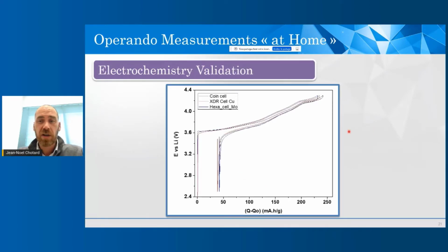So we have to check also the electrochemistry of our cell, and I'm comparing here the galvanostatic curve of NMC material, so lithium, nickel, manganese, cobalt oxide. Maybe it's not that visible, but you have a black, a red, and a blue curve right here. The black was measured with a regular coin cell, the red was measured with the old cell that you saw previously, the big one, and the blue line has been measured with the hexagonal cell.